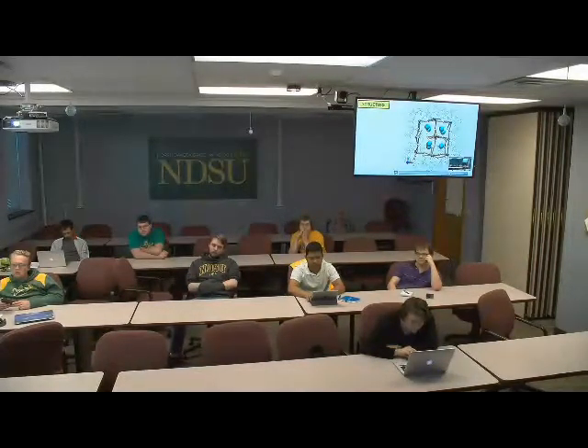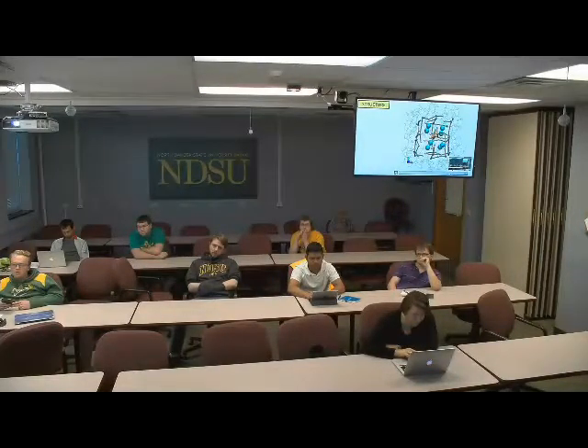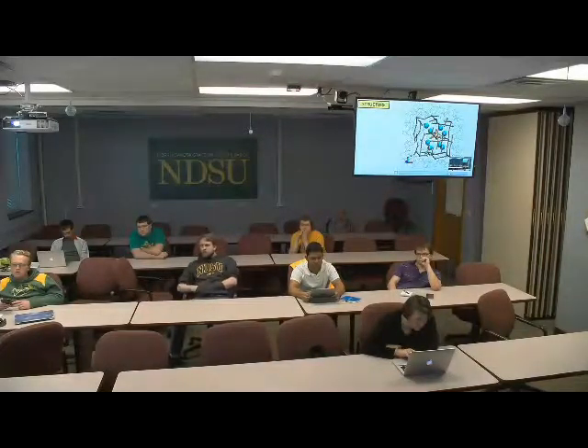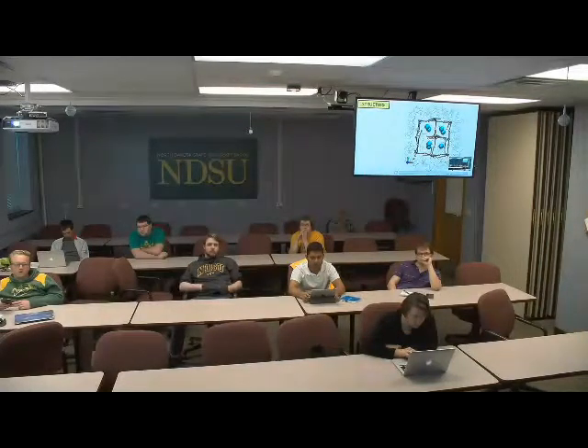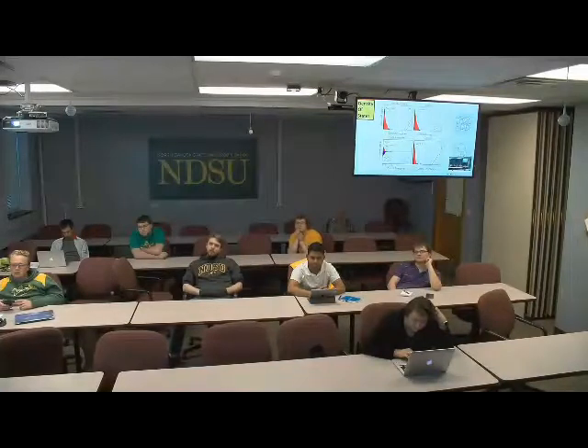Here is the structure: the scaffold of the perovskite, the semi-transparent ligands, and these blue cyan spheres are cations of cesium. Without spin orbit, the gap will be bigger. With spin orbit, it shrinks by more than half an electron volt. And if one includes spin orbit, one would allow originally forbidden transitions with flip of spin.